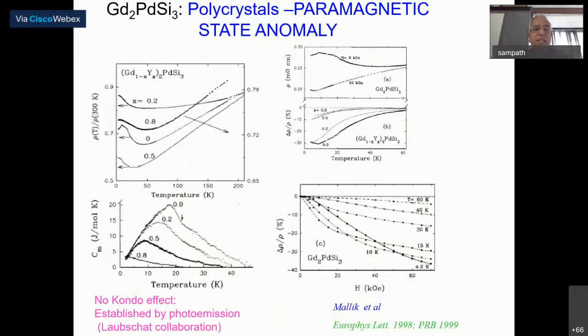This is the data which I presented in 1998 at a conference in honor of Professor Joshi. Therefore, I'll spend a few minutes on this. The electrical resistivity as a function of temperature. I measured as a function of yttrium composition, diluted the gadolinium sublattice. This is a very well-defined minimum you could see here. This is a positive temperature coefficient, paramagnetic state.